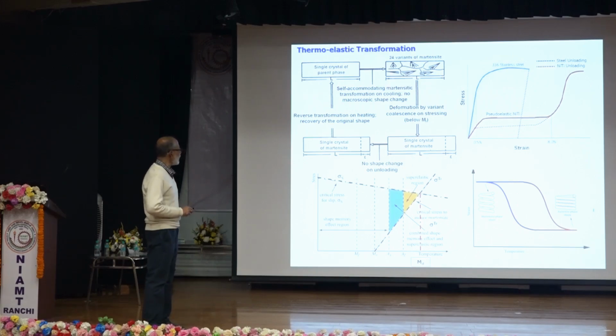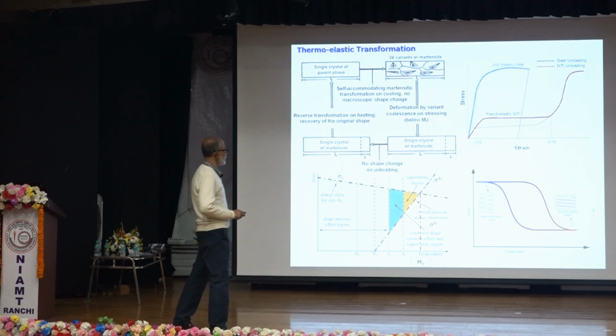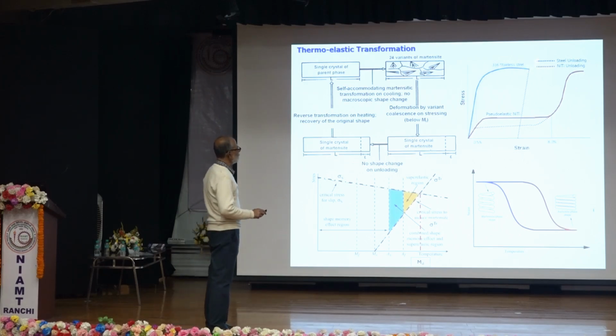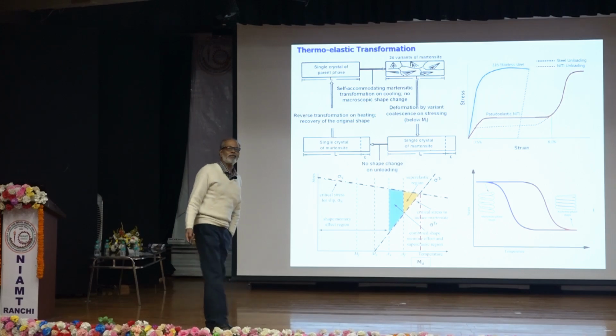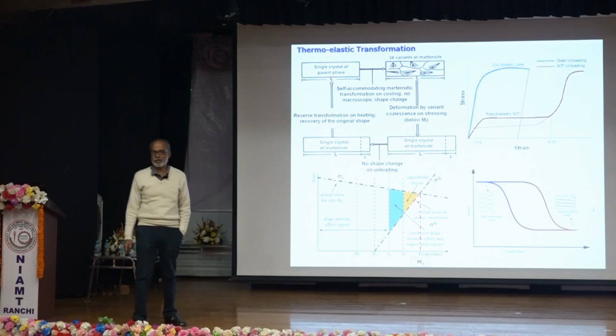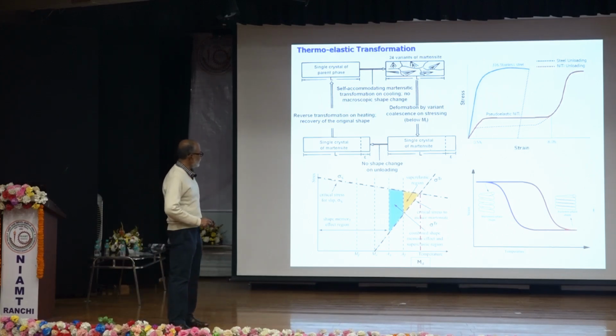Now, there are two possibilities. Why does it happen? It is by virtue of its stress-strain behavior. If you look at steel, if you stress it and withdraw the load, there is a maximum of about 0.5% strain which you can recover. That is the elastic strain. But in the case of nickel titanium alloy, first it is elastically deformed and then the strain is accommodated within a certain plateau. That is, martensite forms, they get twinned, right? But there is no necessity of stress increase. Once that is saturated, once it reaches the CRSS, critical resolved shear stress, plastic deformation occurs. That is how it behaves.